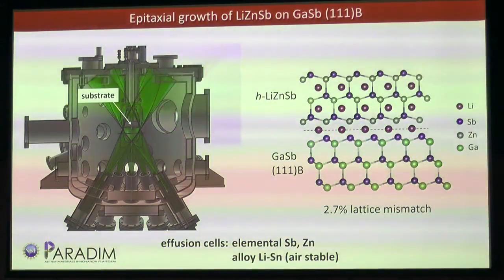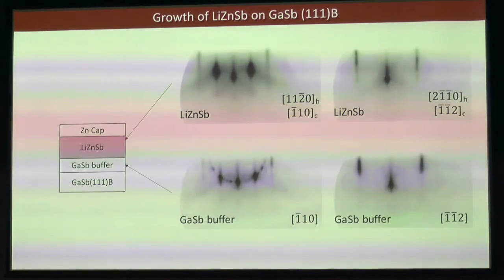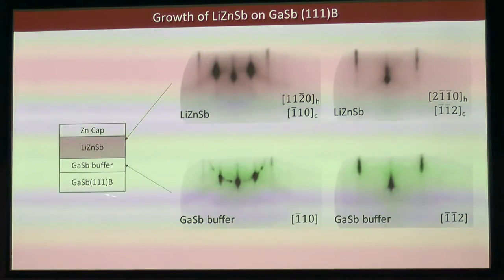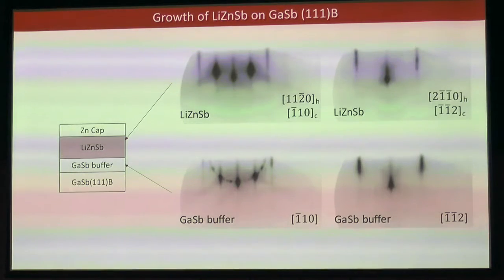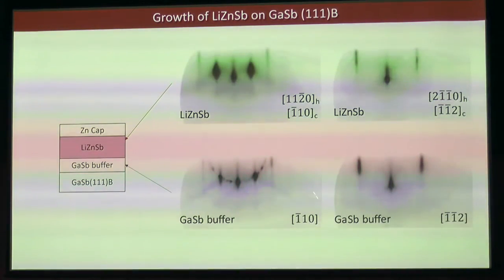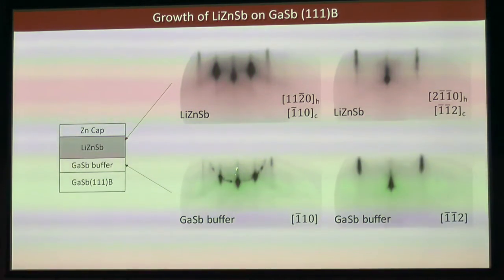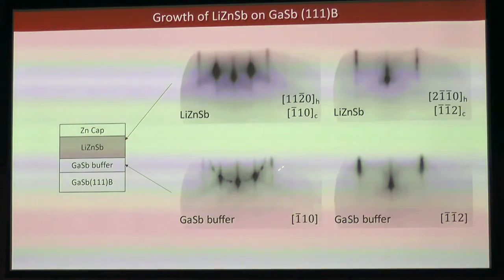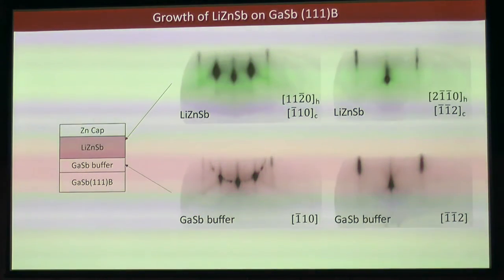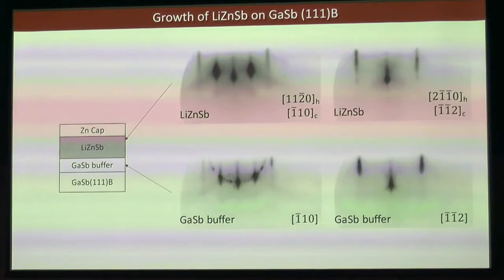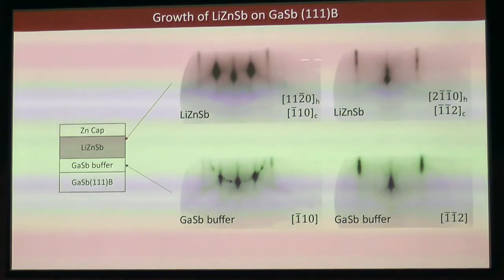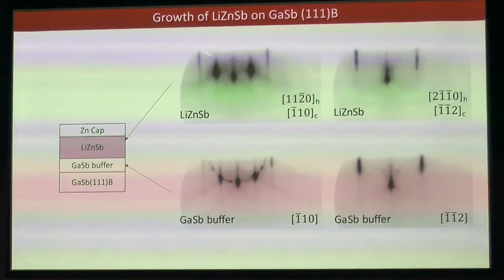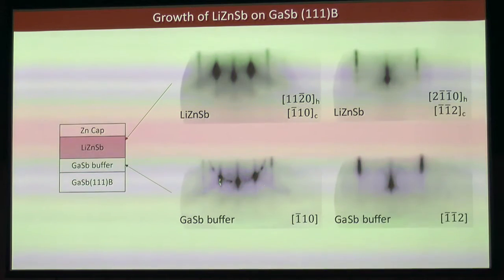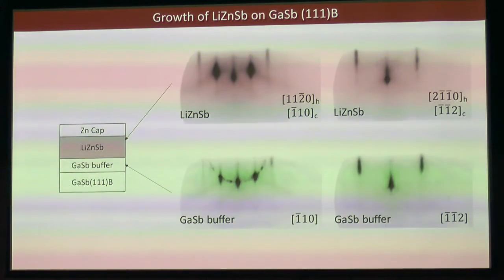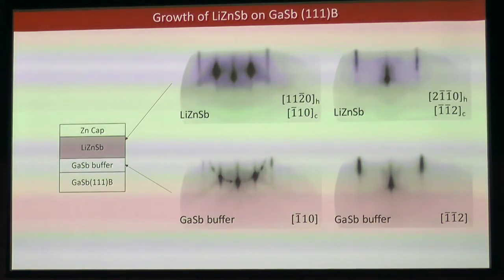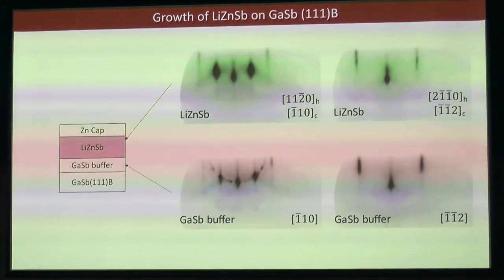Okay. Our sample structure looks like this. Typically, we'll take a gallium antimonide 111B surface and grow a gallium antimonide buffer layer. Here's what the RHEED pattern looks like: sharp and streaky patterns with a hint of a ring of spots, indicative of a reasonably smooth surface. And then we grow lithium zinc antimonide on top. Near lattice match, this 1x2 reconstruction goes to a 1x1 reconstruction, indicating that we've grown something smooth and epitaxial. So let's figure out what we actually grew.